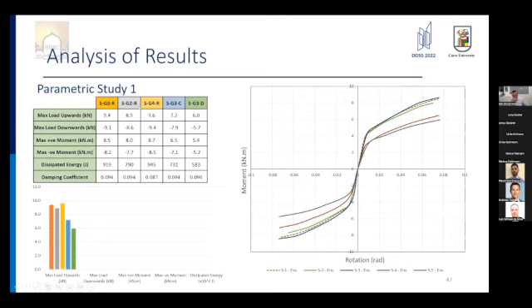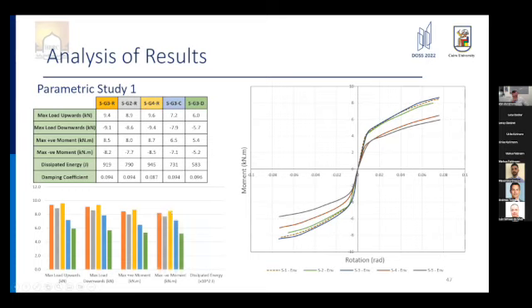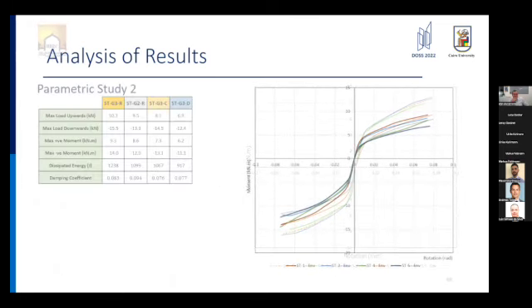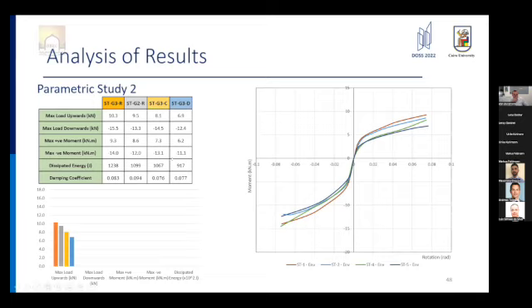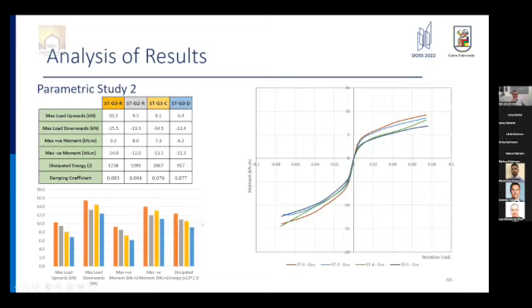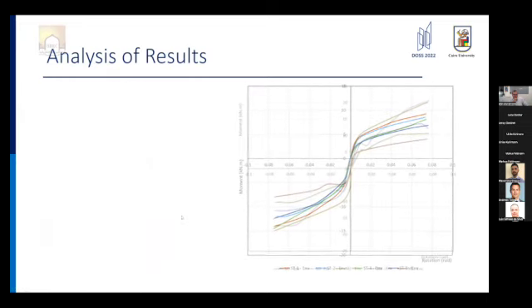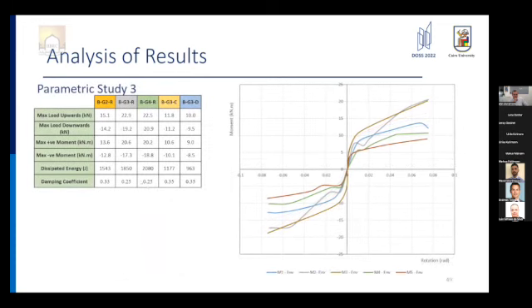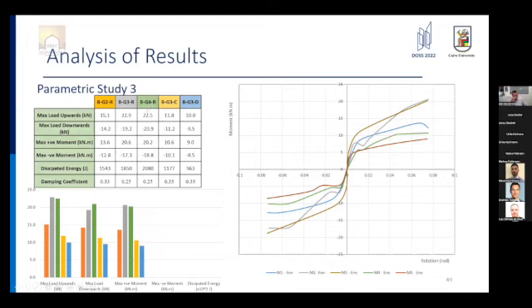The first parametric study focused on the use of self-drilling screws only. So G4R provided the best performance. However, there were only slight differences in moment capacity or energy dissipation when changing the gusset plate thickness. The second parametric study focused on the use of screws in addition to a top plate. Also, the one with the highest gusset plate thickness was dominant. The third study focused on the bolted connections, and G4R, or the gusset plate thickness of 4 millimeters, wasn't superior in all cases. There were cases, especially when loading the specimen upwards, where the gusset plate thickness of 3 millimeters was better.